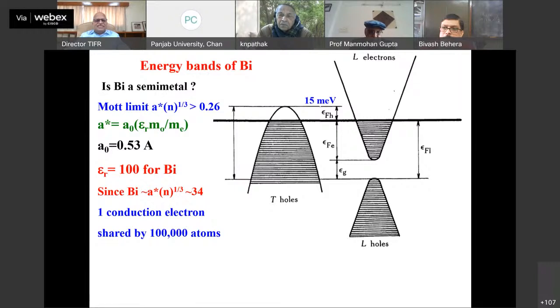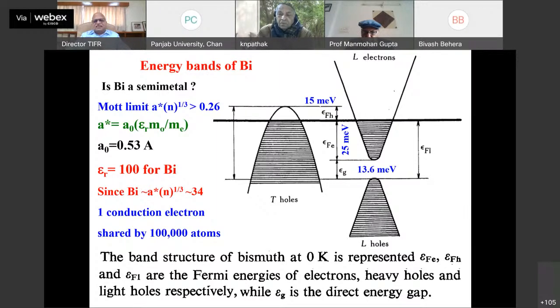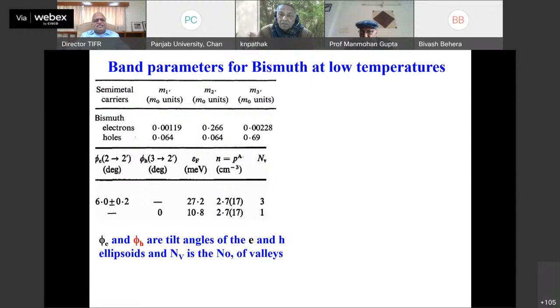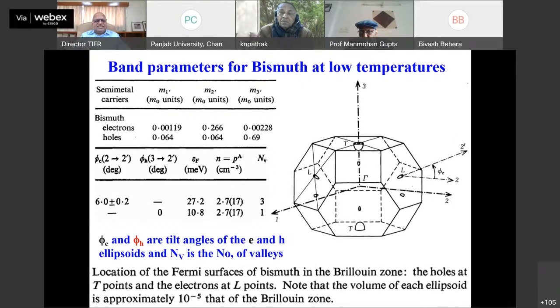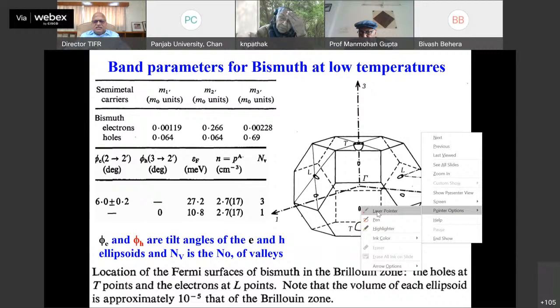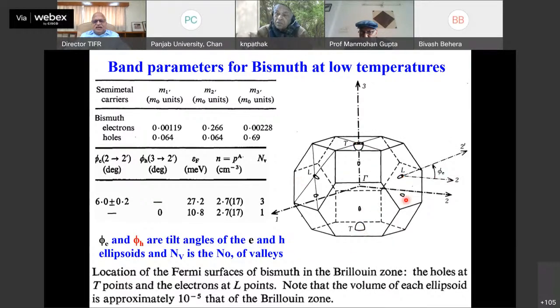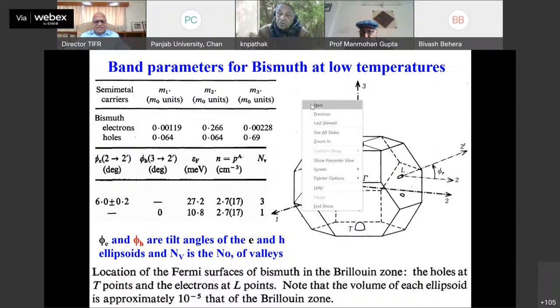So the band structure of bismuth, as I said, the top of the valence band here is higher than the bottom of the conduction band. So there's an overlap of the conduction and valence band here, and most of the peculiar properties of bismuth come because of that. One good thing about bismuth is that it has been studied for nearly 40, 50 years. Everything is known about electronic properties, Fermi surface, everything is known. It so happens that, in this 10 to the power of -5 of the Brillouin zone, there is one hole pocket here. So this is the one hole pocket, and these are the 3 electron pockets. So the properties of bismuth hinge on these electron and hole pockets in the system.